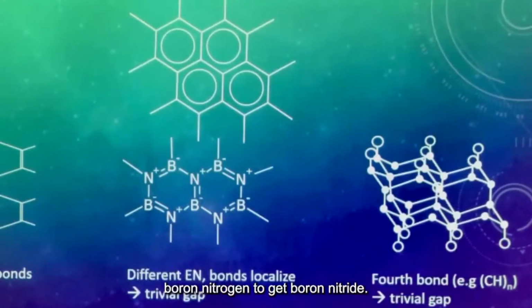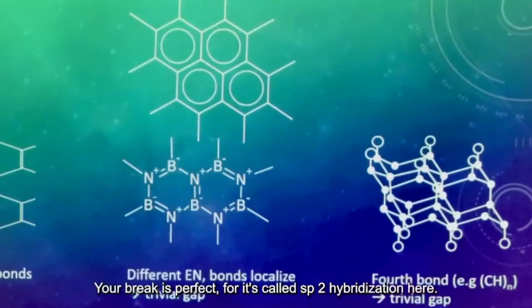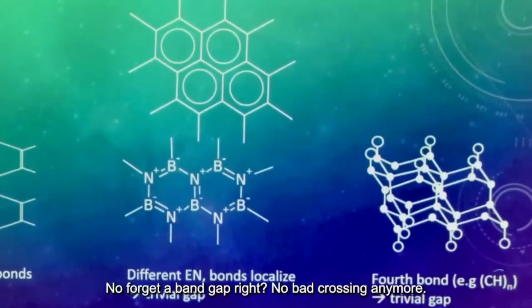Or if we do anything else to mess with these bonds, let's say different electronegativities like boron and nitrogen, we get boron nitride. That's a massive band gap, no band crossings, all open. We attach hydrogen, actually we start to buckle it. We break this perfect, what is called sp2 hybridization here. Now we get a band gap, right? No band crossing anymore.